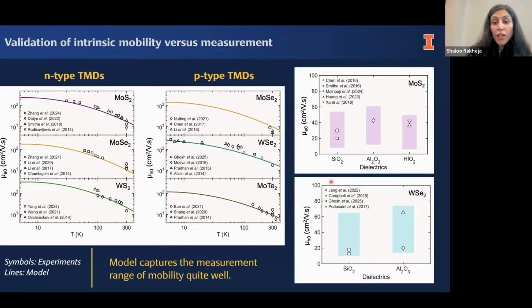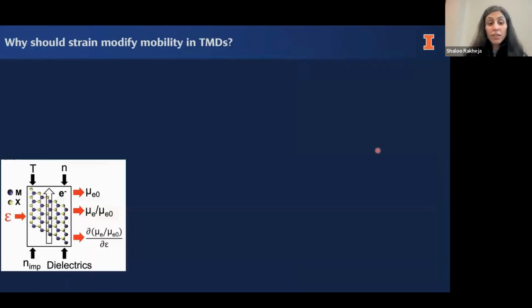Not only that, we've been able to validate that our model predicts the experimental mobilities of these materials for different dielectric environments, which is also very exciting. So what I would like to emphasize is that within the expected experimental sample variations and environmental factors, our model is very robust because it is allowing us to calibrate it and predict the mobilities for a very diverse set of conditions. Okay, so that was my baseline.